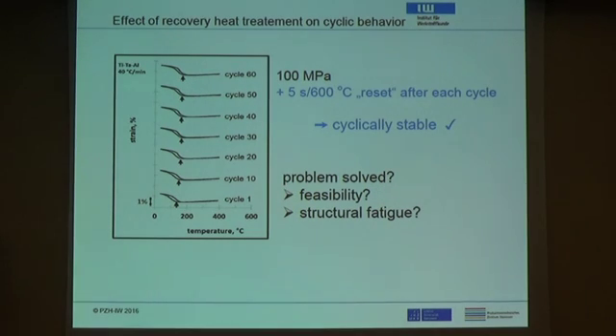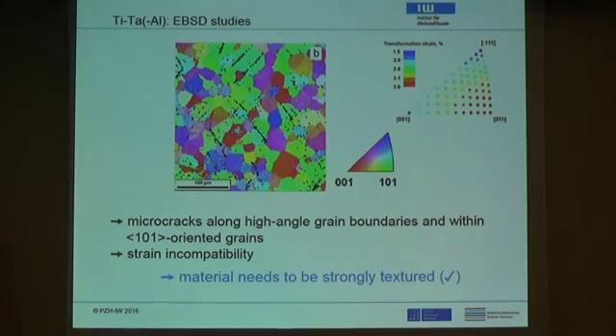I'm not so sure, because for an actual actuator, it might not be possible to shortly heat this up to 600 degrees C. And then there's, of course, the issue of structural fatigue. After these cycles, we looked at the surface of the sample, and this is an EBSD study here. What you see here is the orientation of the individual grains. And these tiny dark features in here are all cracks.